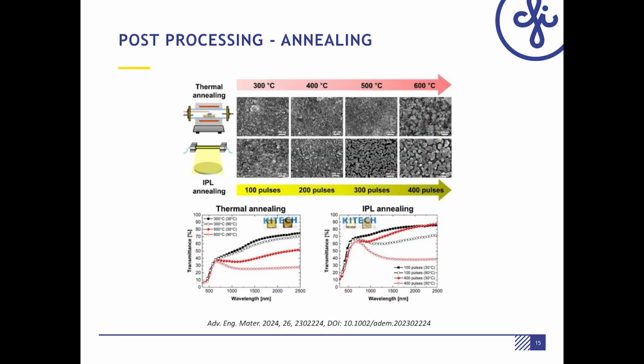After deposition of vanadium dioxide, annealing is needed to improve thermochromic performance. That may be thermal annealing or light annealing. In both cases, at proper parameters, nice thermochromic performance of vanadium dioxide thin films can be achieved.